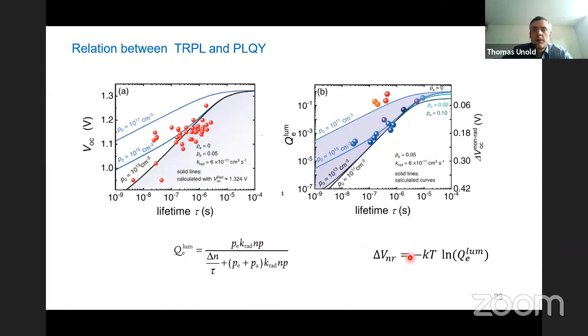From the quantum efficiency, you can calculate the non-radiative loss or also the VOC if you want. Sunny Sindri talked about that. And if you look at the data again, now you can see that mostly they lie on the expected line. There are some variations in the expectation from theory with the doping. If you have very high doping, then you could have a higher VOC, and also a higher quantum efficiency. But that can explain some, not easily these low values. And there are also some high values in the literature that are not so easy to explain. There can be many reasons for that, and I will go into some. So what can be problems with the PL quantum efficiency and the lifetime measurements?